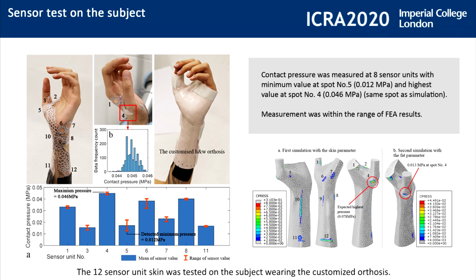The 12 sensor unit skin was tested on the subject wearing customized orthoses. Contact pressure was detected in 8 out of 12 sensor units with a range from 0.012 MPa to 0.046 MPa. It was expected that no contact pressure was measured from the other 4 sensor units because of too little pressure, as the tissue at the 4 locations is very soft, closer to fat.